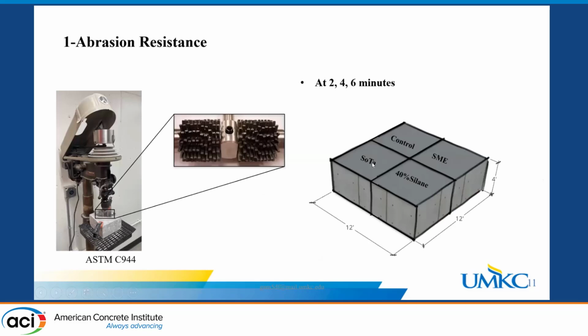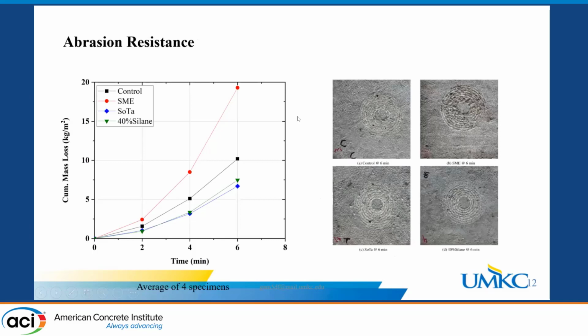The first thing we looked at is the abrasion resistance of concrete. After we cast and cured our specimens, we tested abrasion resistance according to the methodology described by ASTM C944. The only difference is that instead of the recommended 2 minutes, we looked at 2, 4, and 6 minutes. The results were unexpected. Soy methyl ester negatively affected the surface abrasion of the concrete. After 6 minutes, the accumulated mass loss was almost twice that of the untreated control.